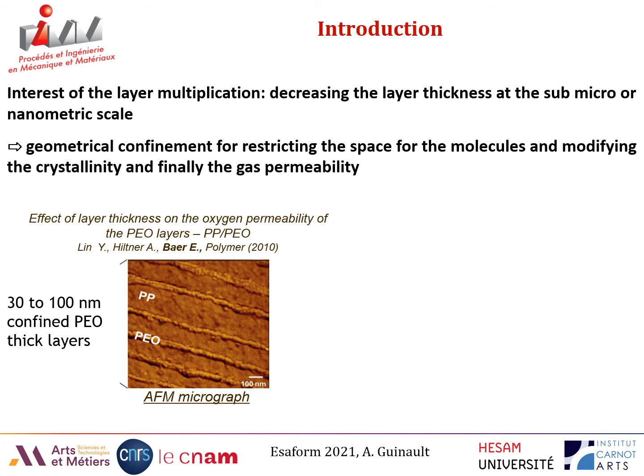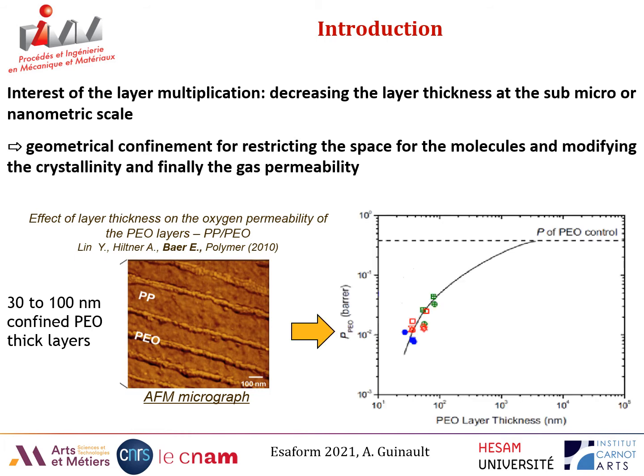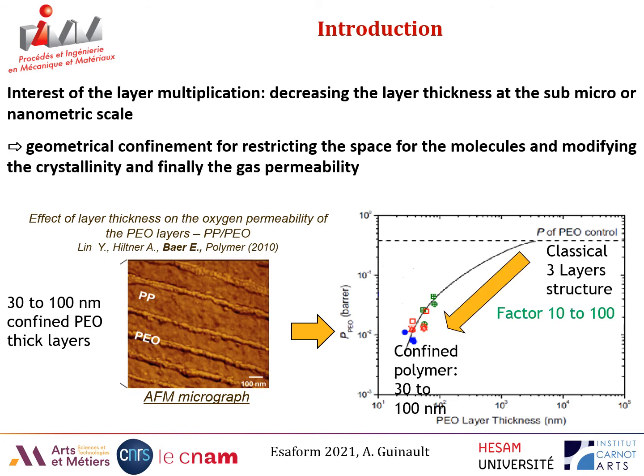And if you look at some work of a Baer team, you can see here a system where PEO, polyethylene oxide, is confined between PP layers, as you can see, at 30 nanometers to 100 nanometers. And you can see that by decreasing the layer thickness of the PEO, you decrease the permeability of PEO inside the film by a factor 10 to 100 when the polymer is confined to a nanometric dimension.